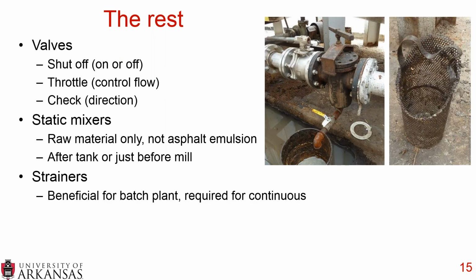And then you also want to have strainers. So strainers can be beneficial for batch plants, but they're required for continuous plants. So you can see the picture on the left that shows a piping system, and that is a strainer in the middle of that picture, with the little sample pipe coming off the bottom of it. That's where the strainer is. And if you open that up and take the strainer out, that's what it looks like on the right. But that keeps clumps from going through. If there's any sort of debris in your tanks, it keeps those from going into the asphalt emulsion mill, and it just provides a more homogeneous product going through your plant.